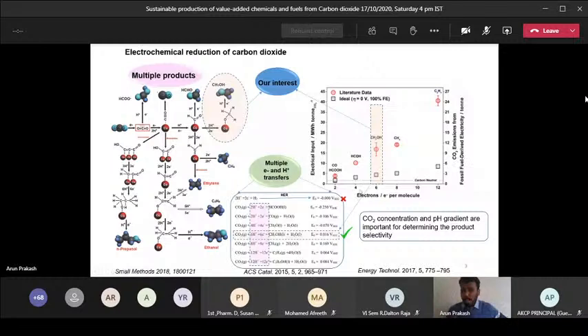the efficiency. Whenever you run a reaction, you always care about the yield or the efficiency, right? So in this case, we say Faradaic efficiency. Faradaic efficiency is based on the amount of charge consumed, your product formed will vary. If the amount of charge consumed is completely converted into the product, then your Faradaic efficiency is 100%. But this is not always the reality. Most of the systems can yield only 60 to 80% or 90% Faradaic efficiency. None of them can achieve the maximum, that is 100% Faradaic efficiency.